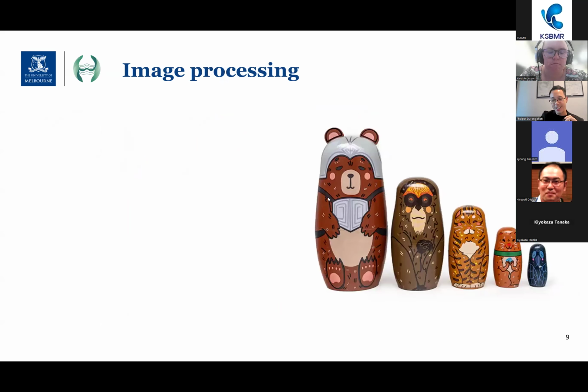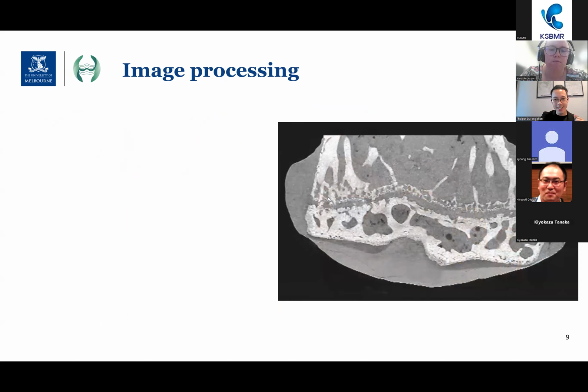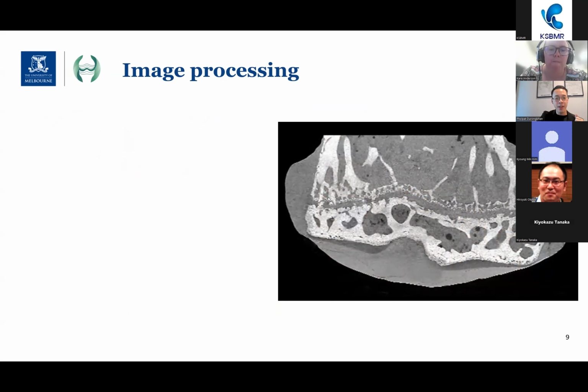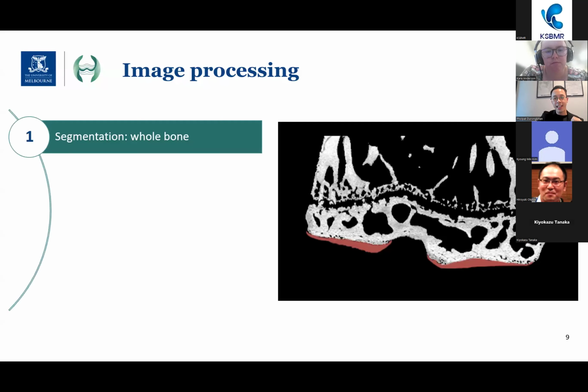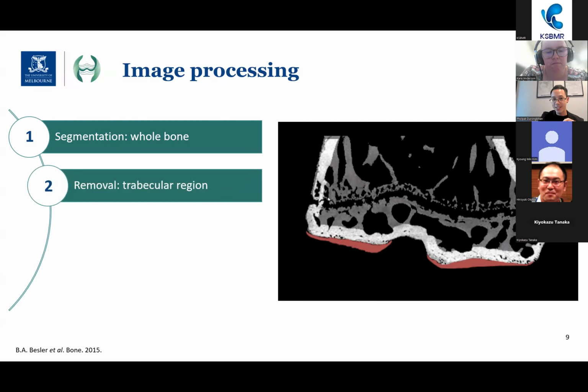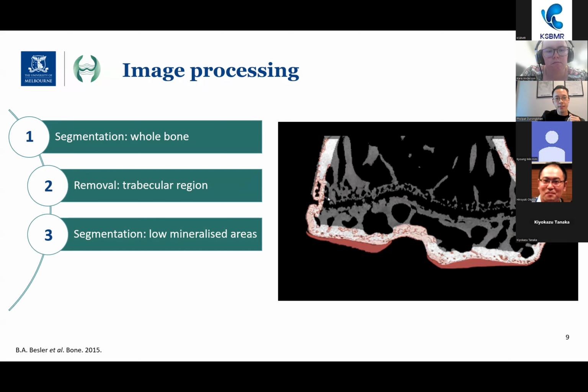For the processing approach, I took a very similar approach to this nesting doll approach. So we segment one layer at a time. This is the image that we get. Then we segment the cartilage out because that's the first thing we can easily remove. The second layer is to get the bone, from which we can define the cortical region and separate the trabecular region from the cortical region. And in this cortical region, you can see that we can use this monochromatic beam to separate the low mineralized region from the high mineralized region within this cortical area.